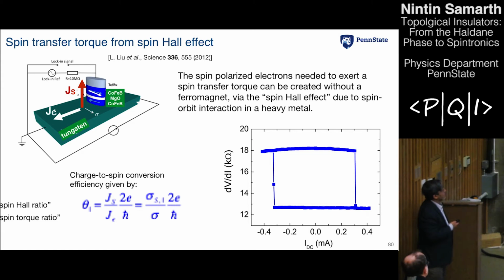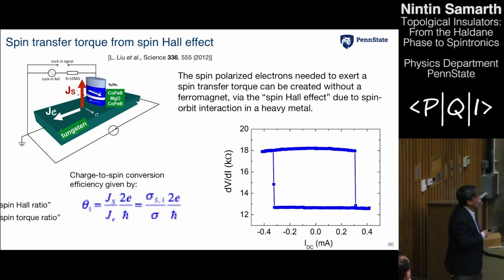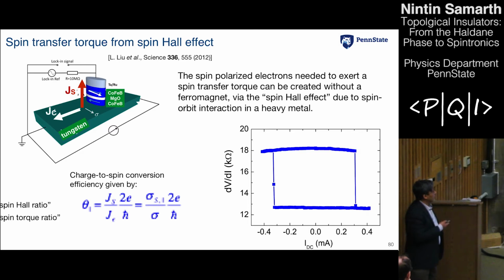And if you now have a magnetic system on top, it turns out that instead of using a magnetic field to change the state of a magnet, you can just use a current. Right? So this is a hysteresis loop, but there is no magnetic field here. This x-axis is a current that's being driven through the sample. And the key thing that matters to people who want to make devices is what is the figure of merit of such a device or such a material. And the relevant figure of merit is something that is called variously a spin Hall ratio or a spin torque ratio. And it's essentially a ratio of the spin current density to the charge current density normalized by fundamental units of angular momentum and charge.